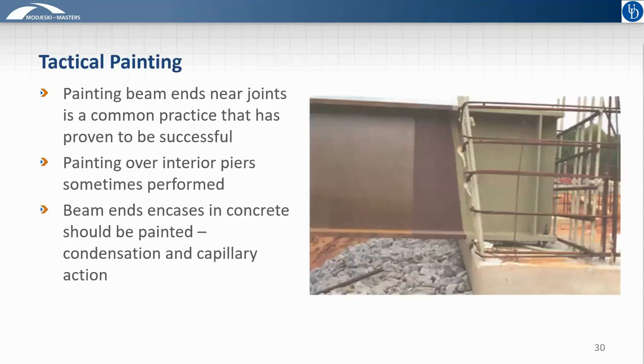One other approach here is a tactical painting of a weathering steel bridge. So painting specific areas where we know are problematic ahead of time is a good way to prevent any sort of future problems with weathering steel. So if you do have joints on your bridge, if you haven't been able to get rid of all of them due to the span lengths or other reasons, then one approach would be to paint the girder just for a short distance either side of the joint. Often states will use 1.5 times the depth of the girder as a good rule of thumb for how much to paint. That has proven to be very successful.